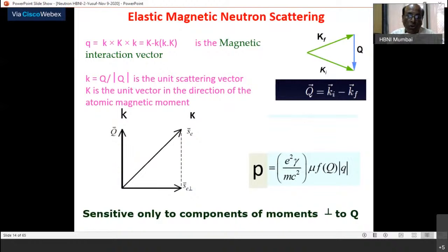You also have to know where those magnetic atoms are sitting in your magnetic unit cell, either at half, 0, 0, or half, half, half, or 3/4, 3/4, 3/4, or 0, 0, 0. That is knowing the position. Third, you have to say, if it is magnetic, how much moment it carries: the ordered moment, not the disordered moment, not the paramagnetic moment.